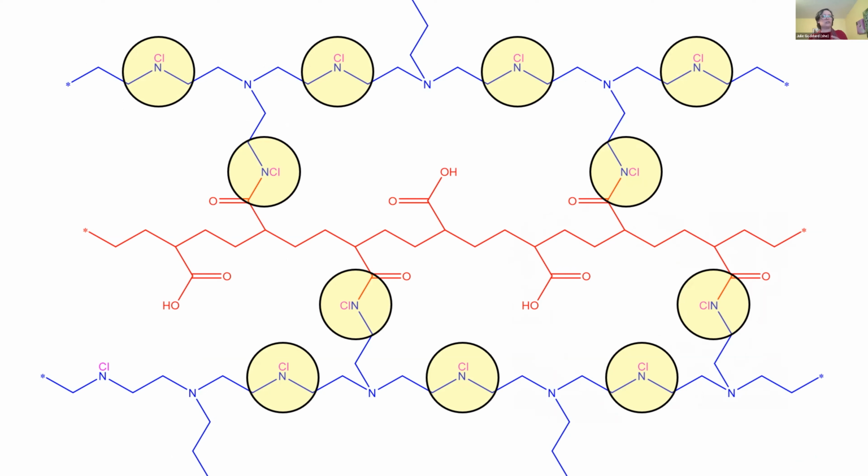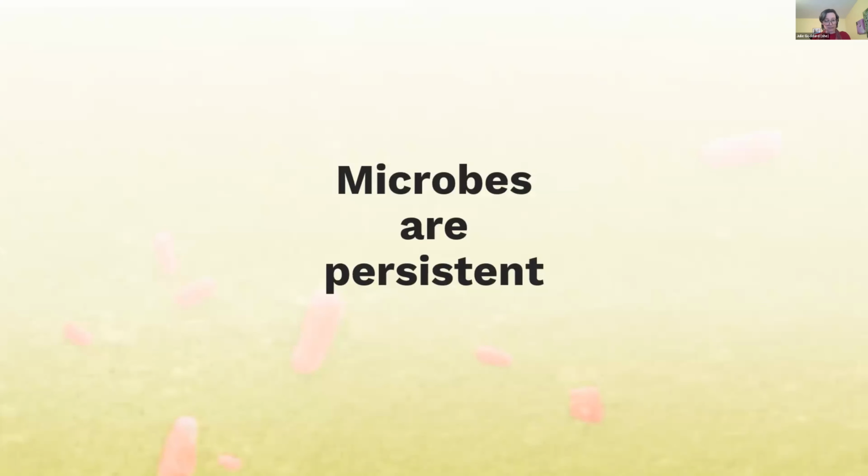And while there are some really interesting conclusions that can be found and reported with these coatings, the reality is microbes are persistent, especially in the nutrient-rich environment of food and beverage processing. And this is why we start to see the prevalence and persistence of the same fingerprint of microorganisms over long times in the same facility. Even the most beautifully designed antimicrobial surface or the most clever non-fouling material will eventually condition with protein and carbohydrates and lipids, the building blocks of all of our food and beverage, right? And can be rendered a beautiful place for microbial adhesion and biofilm formation.